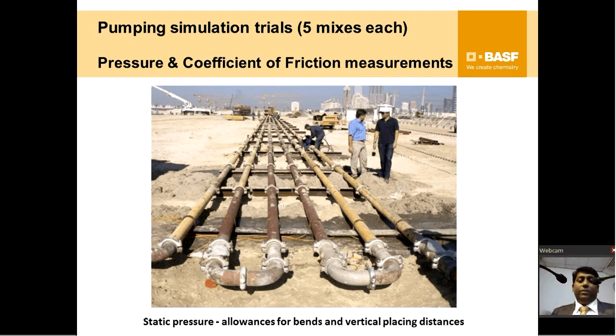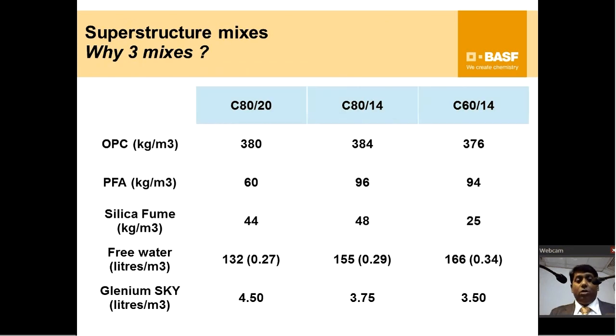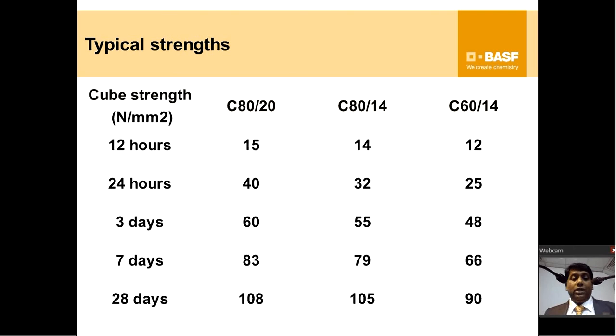Then we did this simulation and found out how the concrete works, what the pump pressure is, all these things were done. Mixes used were C80 with 20 mm aggregates, C80 with 14 mm aggregates, and C60 with 14 mm aggregates. So this is the mix here, 380, 60 and 44, free water, admixture in, 384, 96, 48 and 3.75, and these were the mix designs used for this particular structure.